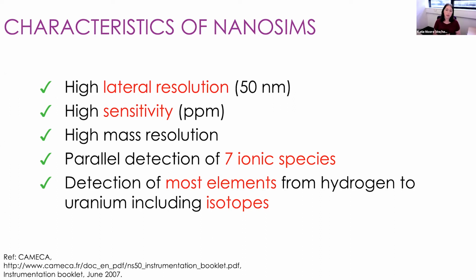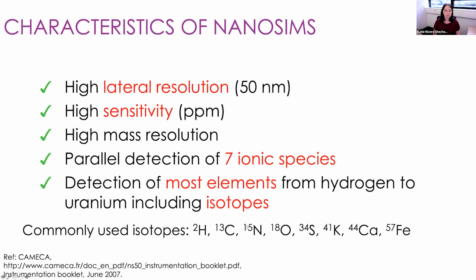And we can do this by either looking at natural variations of isotopes, as I mentioned in meteorites, for example, but we can also deliberately introduce enrichments of naturally occurring isotopes that have very low abundances. So we can track the uptake and incorporation of elements over time. And so commonly used isotopes that we use in the NanoSIMS are listed here. And in this particular presentation, I'm going to focus a lot on how we've been using deuterium, but I'm also going to show you an example of oxygen 18 as well.